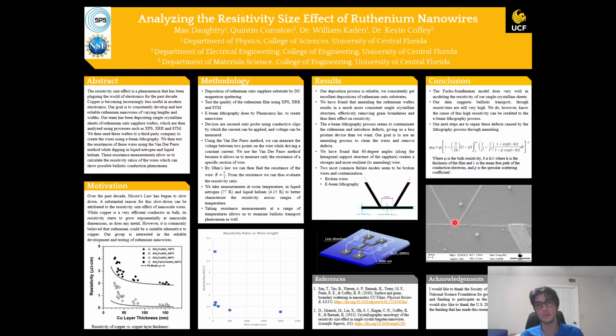So altogether, our resistivity data seems to be modeled very well by the Fuchs-Sondheimer model for the resistivity of the single crystalline sheets. Not necessarily the wires, but that's probably mostly due to the defects that we've added through the lithography process. Again, our data does suggest ballistic transport, although the resistivities are still very high. We do, however, know that high resistivity can mostly be credited to the lithography process. So naturally, our next steps are to try to get those wires back to their pristine state and eliminate any defects and contamination that was introduced with the lithography process. This will probably be done using an annealing process and maybe some other things along with it.